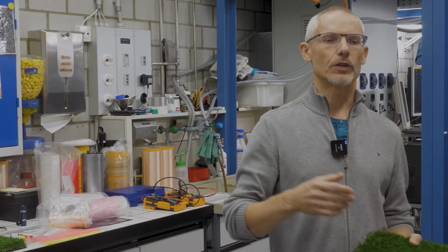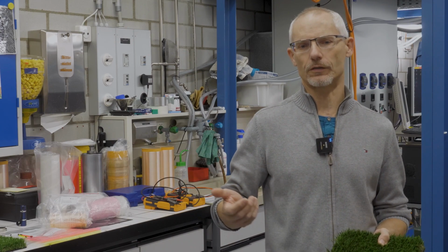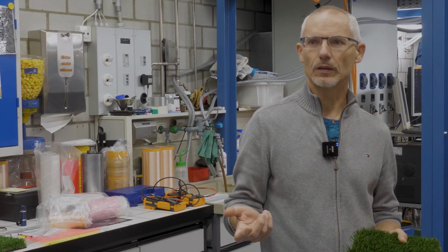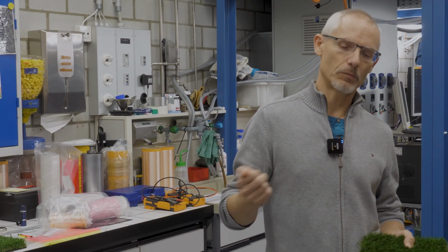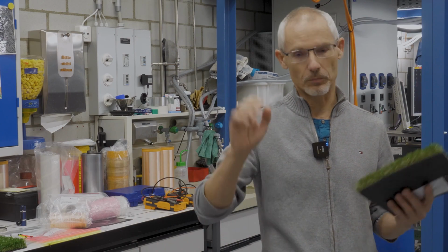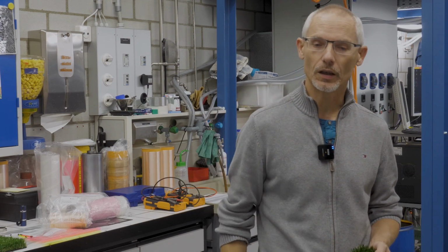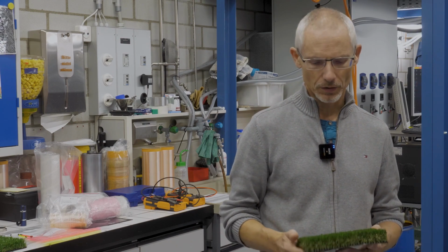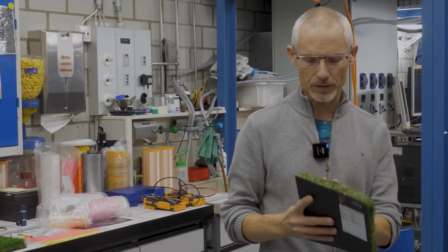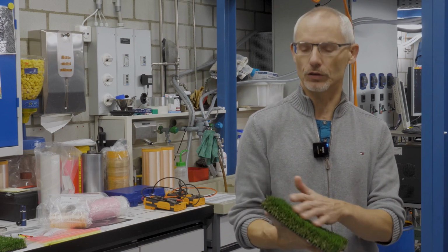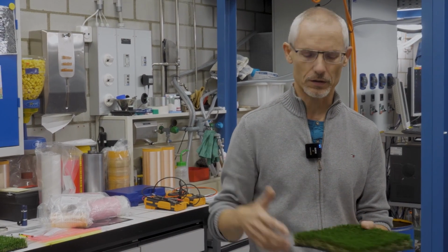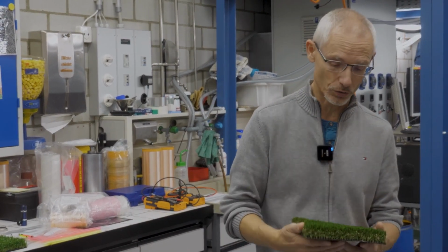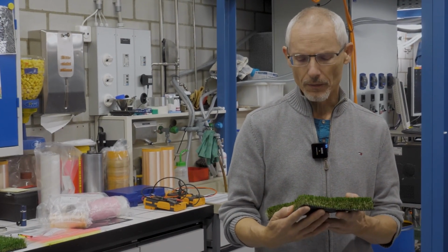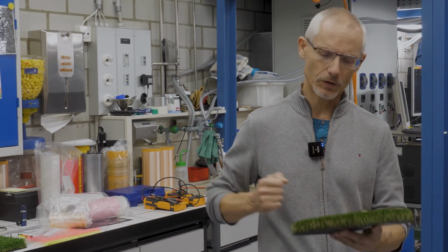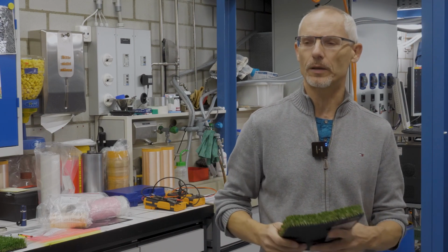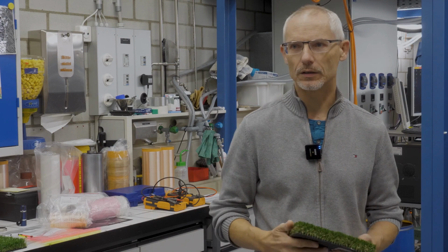Polyamide is a polymer which, for example, is used to spin fibers which are used for toothbrushes. And they are used for toothbrushes because when they're made out of polyamide, you can use the toothbrush for a month, maybe even more, and the fibers still stand straight. And you also want the same to be true for artificial turf. You don't want the material to lay flat, otherwise the ball would roll very fast, it would not look nice. So you want to have straight fibers. But the problem about polyamide is when you slide on a carpet made out of polyamide, you get heavy skin burns. It's a problem of polyamide.